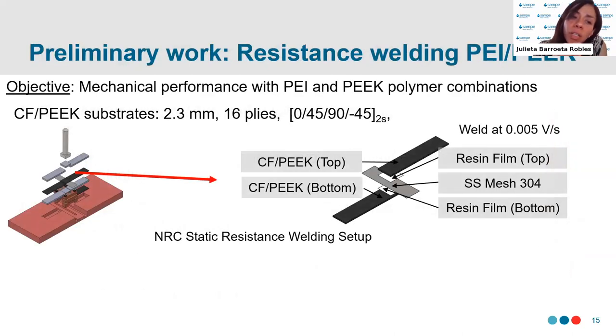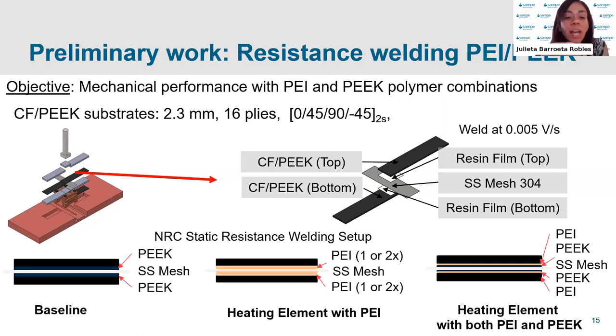There was some preliminary work conducted based on the Thermabond process using resistance welding. The objective was to evaluate the mechanical performance using both PEI and PEEK. Using carbon fiber PEEK substrates and the NRC static resistance welding setup, specimens were welded in a single lap shear configuration using stainless steel mesh as the heating element. Three configurations were explored. A baseline, which had a PEEK resin film surrounding the stainless steel mesh heating element. Then one or two layers of PEI on each side of the heating element. And finally, a hybrid heating element, which had both PEI and PEEK.